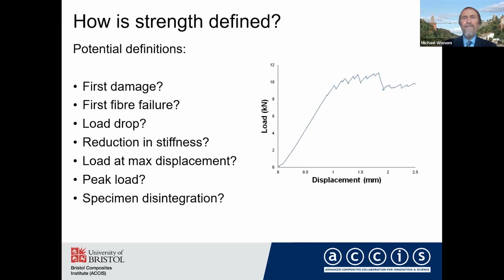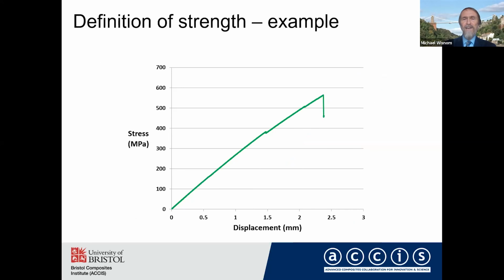So first of all, let's talk about how strength is defined. There are lots of different ways you can define strength. If you do a test, you may get a load displacement graph, which may have quite a complex form. Do you define the strength as the first damage, the first fiber failure, the first load drop, when you get a reduction in stiffness, the load at the maximum displacement, the peak load, or just when the specimen completely disintegrates? Lots of potential definitions.